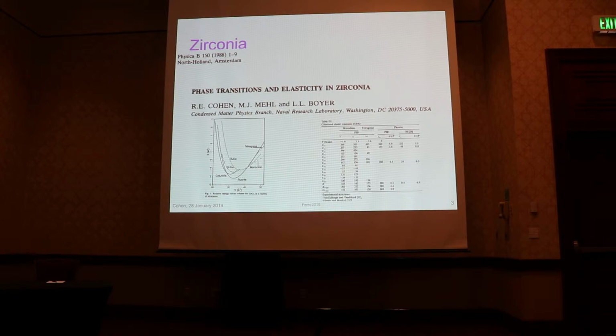Now, actually, I've forgotten more about zirconia and Hafnia than I ever knew. It was actually one of my first papers, and I didn't even remember this, that my first paper as a postdoc was actually on zirconia. And I looked at these phase transitions of these different phases, not with self-consistent density functional theory, but with a model, a first principles based model that wasn't perfect, but trying to understand the stability of these low symmetry phases. Interestingly, the ground state in both Hafnia and zirconia is monoclinic with 7 coordinated zirconium, and it's just very strange to begin with.